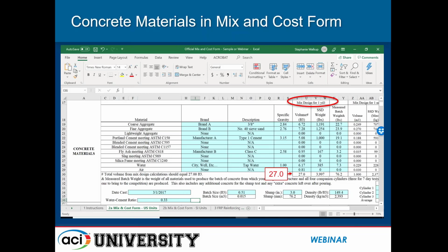Correct. So that is what they actually would put into the mixing drum or into their pan to actually mix their beams, their cylinders, the slump cone, and any excess. So that measured batch weight is the material that they are physically measuring out in their lab environment and truly mixing so that they can cast their member, their cylinders, make their slump cone, and give that measurement and any excess. That is correct.